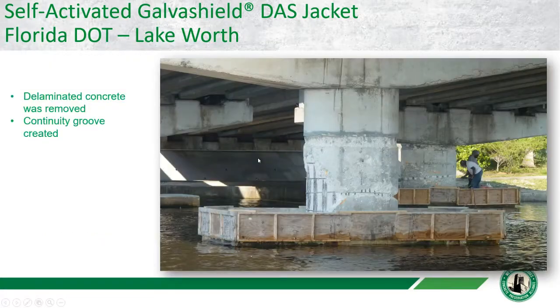So originally, this column had a standard concrete jacket based around it. You can see where the height of the standard concrete jacket came up. Again, this wasn't controlling the corrosion or stopping the corrosion, so the jacket was removed. And you see the jacket was removed, corrosion was occurring underneath, so all of the delaminated concrete was removed.